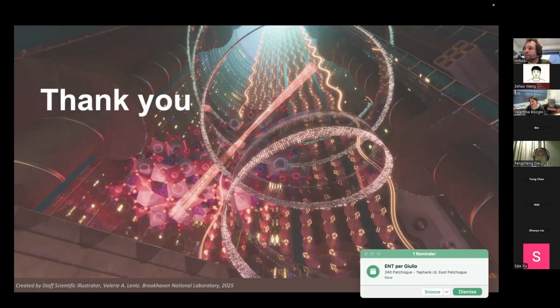And can you say if there's some time resolution to this technique, or can you only measure in DC basically? Suppose there's some transient spin current, let's say optically generated or something like that. In the mode I've presented here from a synchrotron, you don't get much of a transient, unless it is something that could happen in the intermediate state, because of the presence of the core hole. There is a lifetime associated with the core hole presence, which for other types of excitation is actually crucial to determine their intensity. But here we are talking about femtoseconds, a few femtoseconds. Otherwise, I would say a free electron laser you need to use, for a real-time dependence. Thank you.